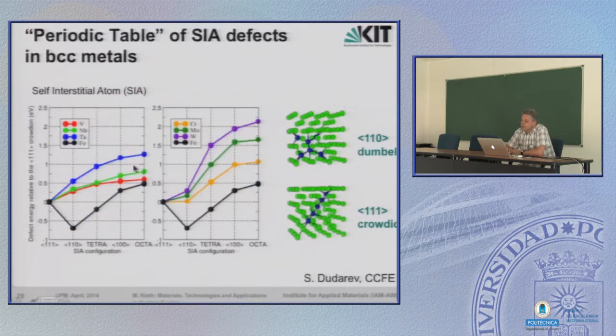But never mind. Here are the energies, the direct energy relative to the crowdion, to the 1-1-1 direction. This we call V0. And now it is important that this configuration, which shows the lowest energy, has the highest stability. In other words, in the blue, green and red curve, the lowest possible energy of a self-interstitial defect is the 1-1-1 crowdion. This means in tantalum, niobium and vanadium, the crowdion is the stable self-interstitial atom configuration. Now you see the black line, and this shows a quite different behavior. Here, not the crowdion, it's the dumbbell, the 1-1-0 configuration is the most stable self-interstitial configuration for an atom.